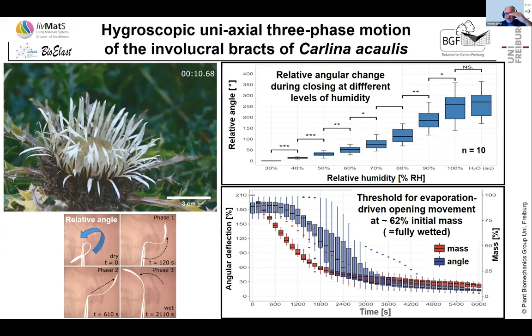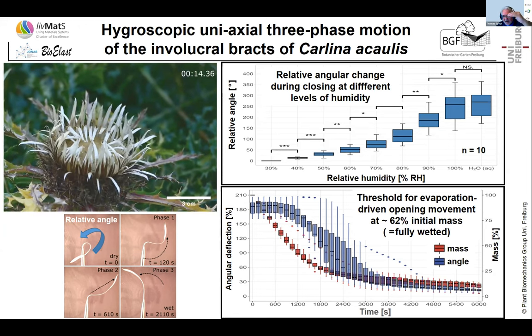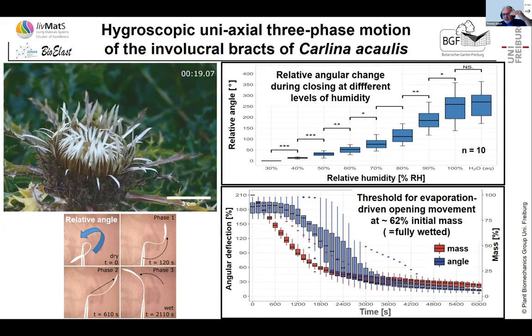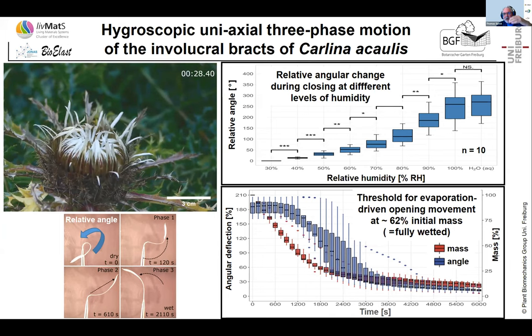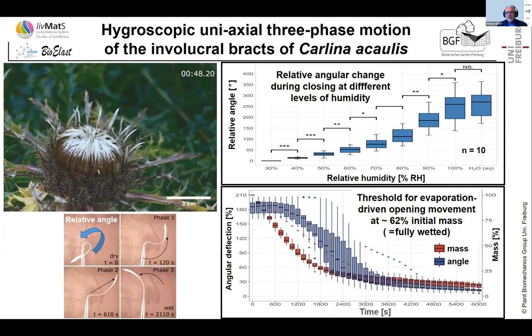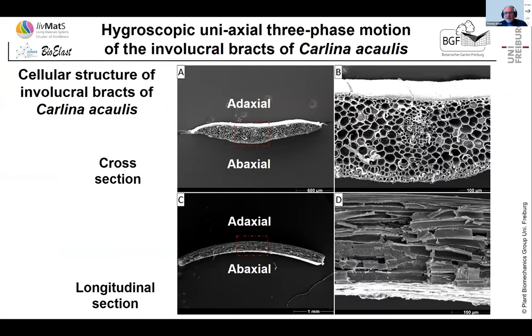And so you say you have a kind of starting phase, and only if the humidity has dropped by 30 to 40%, then the motion starts. And all this is embedded in this tiny structure. This is an SEM of the cross section of one of these leaves. This is an SEM of the longitudinal section. And you see it consists of about 20 cells.